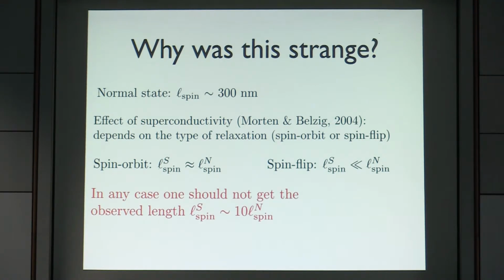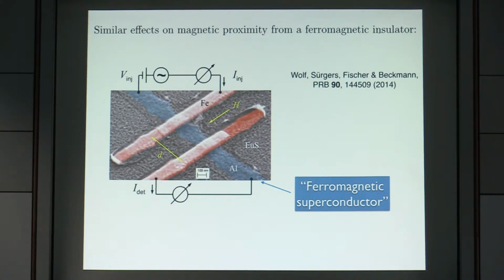So at first we didn't actually understand these experiments at all. But then there was one additional piece of information a couple of years later. The same group measured these spin injection experiments in systems where the aluminum was next to a ferromagnetic insulator, and they got essentially similar results in this case. The ferromagnetic insulator was giving a magnetic proximity effect to the aluminum, and they still studied what happened to the spin signal. Roughly similar things happened.